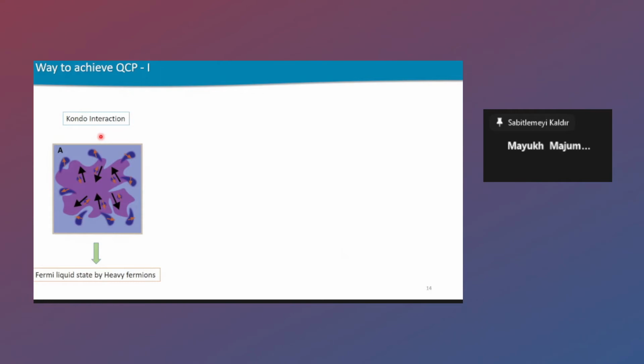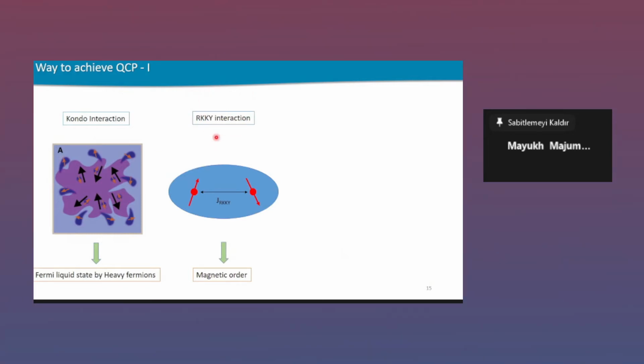Along with the same, at the same time, we also have another kind of interaction called the RKKY interaction, where the 4f moments interact with each other via this interaction. And that actually promotes a long range magnetically ordered state. So now we see that in these 4f-based heavy fermionic systems, these two interactions are competing with respect to each other. Thus there is a finite chance that you can end up with a quantum critical point if you tune these two types of interactions.